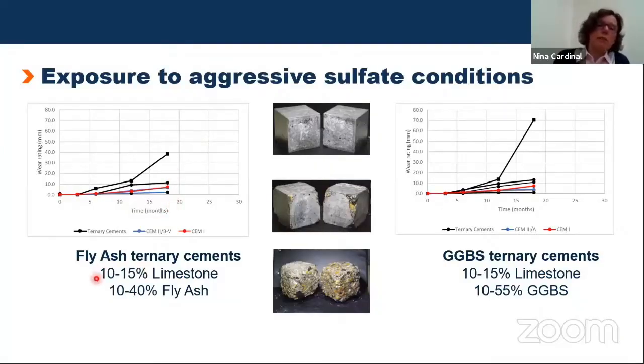The cements were made with 10 to 15% limestone and 10 to 40% fly ash, the remainder being a Portland cement, CEM1. And the dark lines are for the new cements, and the blue line in particular is a control cement, a fly ash control cement.